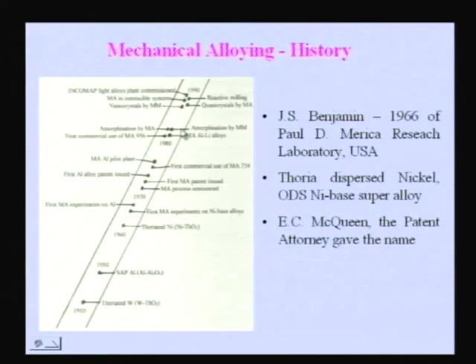And then you have some interesting things that have taken place. For example, amorphization by mechanical alloying, all metastable materials. In fact, before the 80s, they are all basically stable materials. People have never really thought that we can use mechanical alloying to produce novel metastable materials such as either nanocrystals or quasicrystals or amorphous materials. So the first experiments were in 1983, amorphization by mechanical alloying, and almost the same year amorphization by mechanical milling.